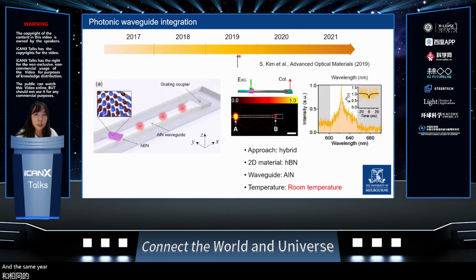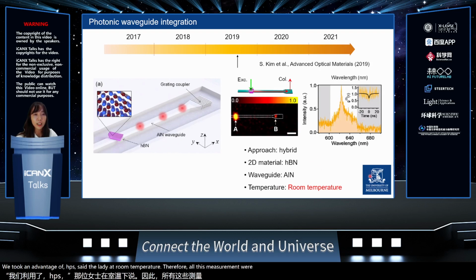In the same year, 2019, and the same month, we also reported a system of quantum emitters embedded in hexagonal boron nitride, coupled to an on-chip waveguide. The single photon emission from an emitter at position A, shown here, was coupled into a waveguide and subsequently scattered into free space by the grating coupler at position B. We took advantage of hBN's stability at room temperature. Therefore, all these measurements were taken in ambient conditions and at room temperature. So this was the first demonstration of 2D quantum light directed into a waveguide at room temperature.